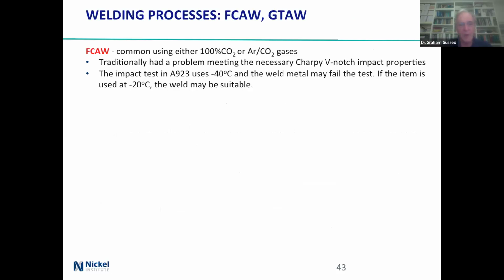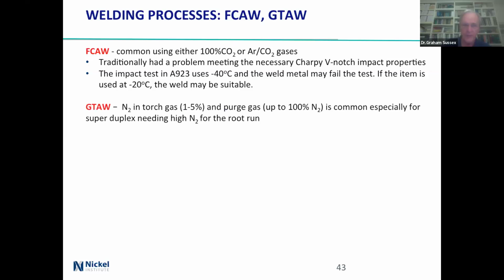Flux cored wire is common, using 100% CO2 or argon CO2 mixes. There has been a problem with getting decent Charpy V-notch impact properties. The impact test in 923 uses -40, and if the item can be used at -20, then hey, the weld may be suitable, but it's a thing that's known and needs to be carefully looked at.